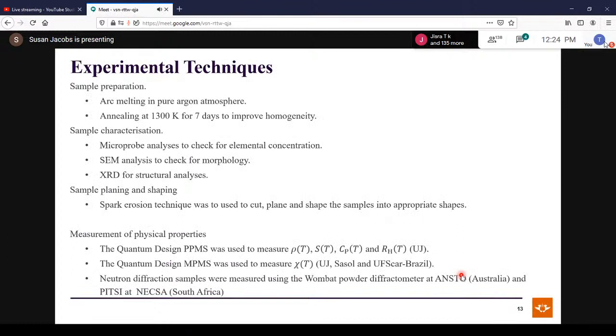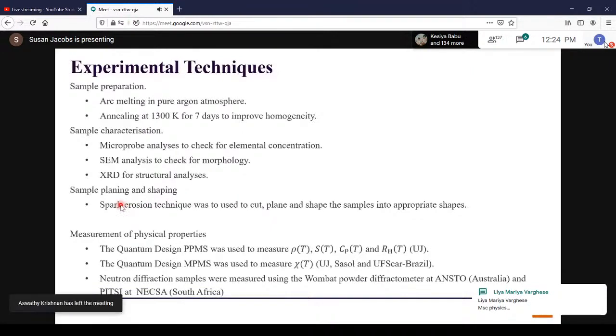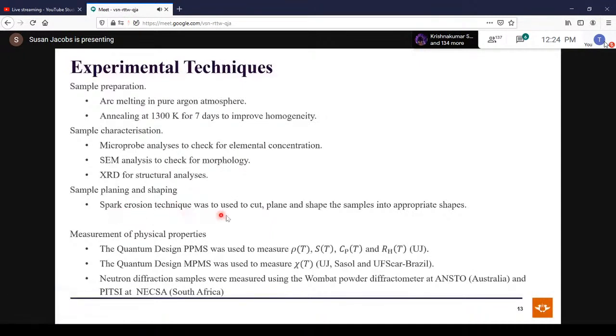Okay, so the experimental techniques. Our bulk alloys were arc melted in pure argon atmosphere. We then annealed them at 1300 Kelvin for 7 days to improve homogeneity, as well as to relieve the stresses that were introduced during arc melting. Then to check the quality of our samples, we did microprobe analysis to check for elemental concentration, SEM analysis to check for morphology, and X-ray diffraction for structural analysis. Then, depending on the measurement we are going to do, we need to plane and shape the samples. For that, the spark erosion technique was used to cut and shape the samples into appropriate shapes.